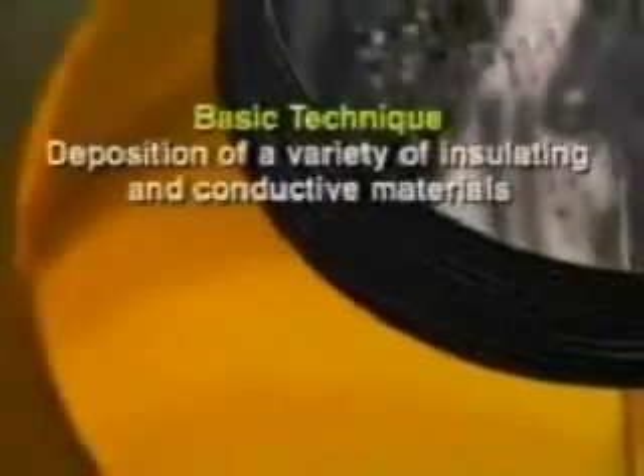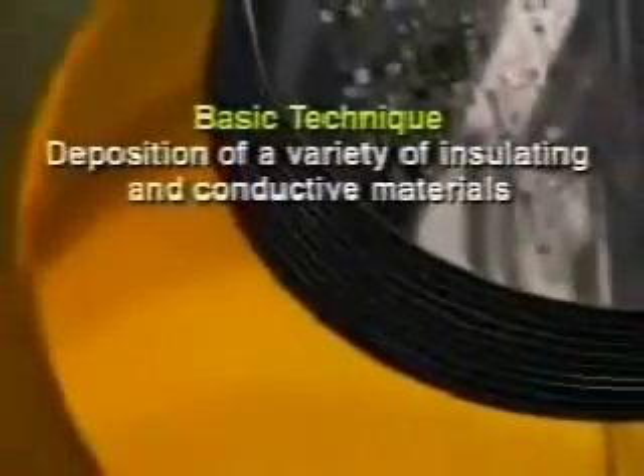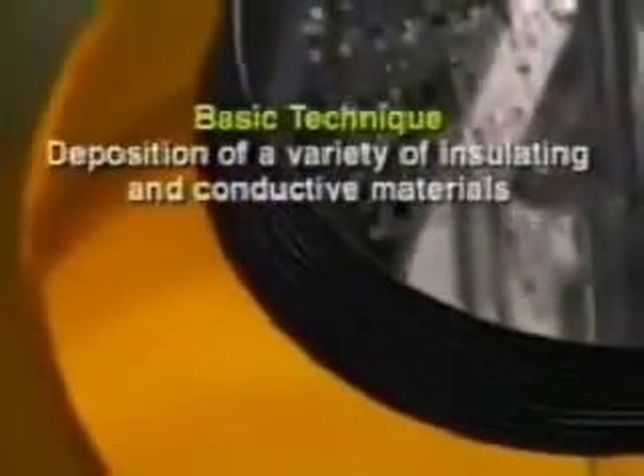In a deposition furnace, a layer of silicon nitride is deposited over the oxide layer. The nitride layer prevents additional growth of the silicon dioxide layer and protects the region where the transistors will be built. Photoresist is again evenly spread on the wafer and baked in preparation for the next mask. Using a computerized machine, each new mask is perfectly aligned to the pattern already on the wafer.